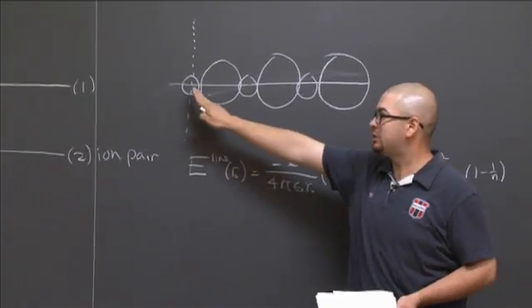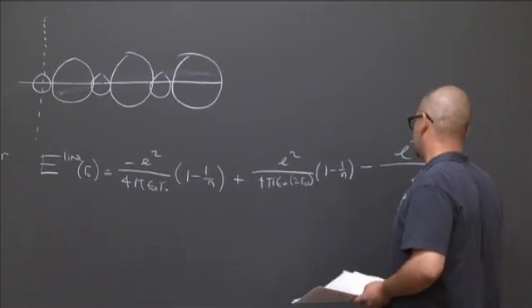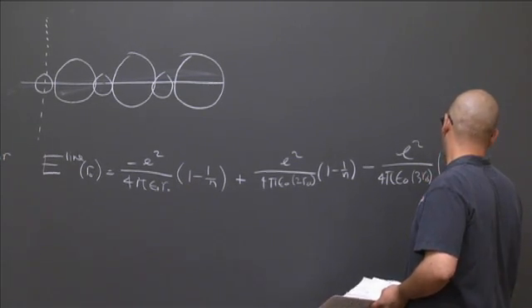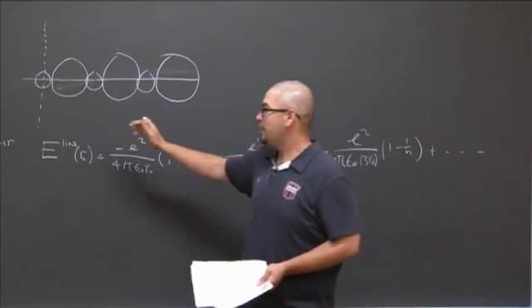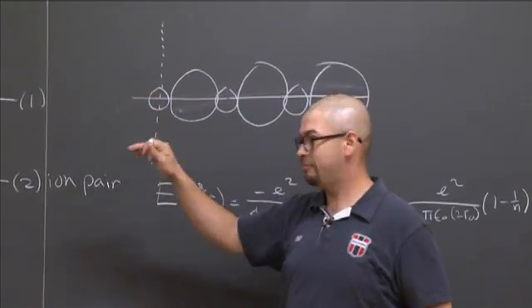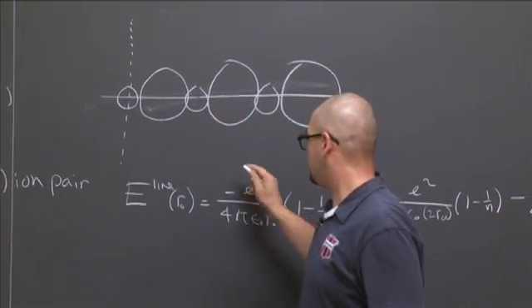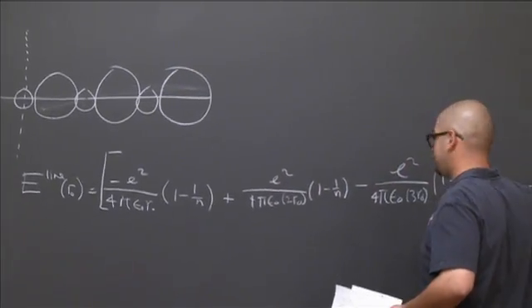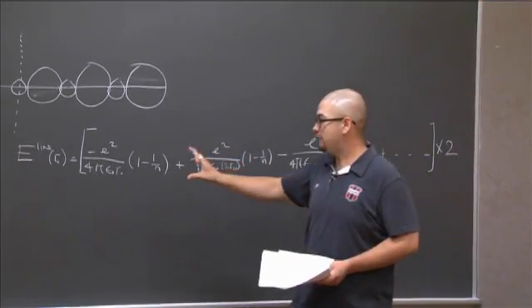Then if you repeat it again, now you're analyzing the interaction energy between the cation and the other anion that's next on the line. So as you can see, you end up getting 4 pi epsilon-naught, 3R-naught, 1 minus 1 over n. And essentially, it repeats until it ends. Now, I'm just analyzing on the right side. Because it extends, it's an infinite line from negative infinity to infinity, then you can also assume that there's an anion to the left. So all you really have to do is you take your overall energy for the right side and you multiply it by 2 because it's additive. So this whole thing gets multiplied by 2, and that's essentially what the energy is of a line.